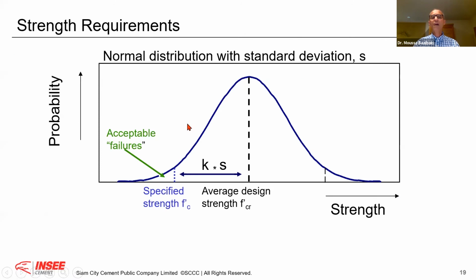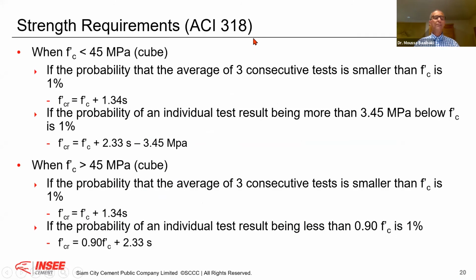That is important because, for example, this is the normal distribution for standard deviation. If you specify, for the design you have to add a factor K multiplied by the standard deviation. And this factor K, if the number of consecutive tests is more than 30, equals 1. Therefore, a professional ready mix producer will normally just add the standard deviation, because the K number should be 1 for him. Now, according to ACI 318, and if you look at the Sri Lankan cases, you have also very similar conditions. If the concrete, for example, is below 45 or above 45, the required strength will be the specified plus 1.34 standard deviation, or this equation, depending on the probability that the average of 3 consecutive tests is smaller than the specified strength. So you take this relation. That is really important.